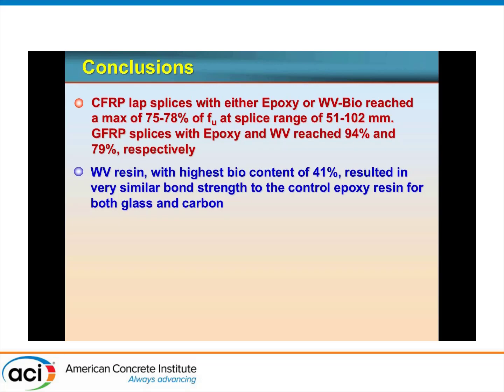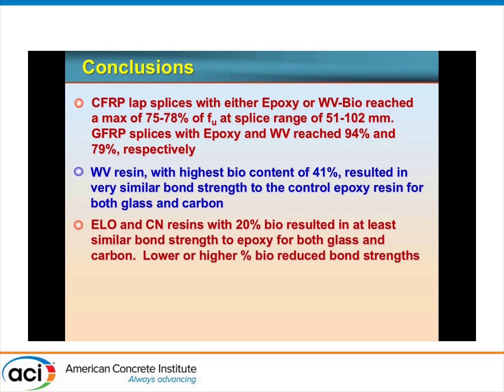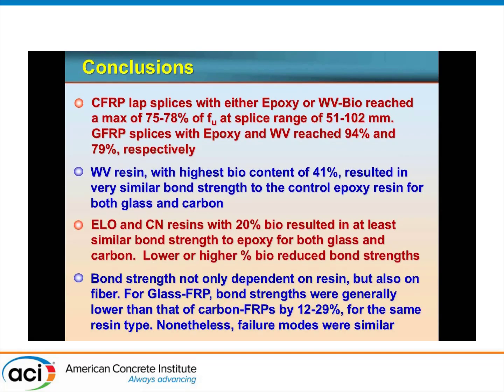The WV resin with the highest bio content of 41% resulted in very similar bond strengths to control epoxy for both glass and carbon. And that's bond to concrete. For ELO and CN resins with 20% bio, it resulted in at least similar bond strengths to epoxy for both glass and carbon. Lower or higher percentage bio affected the bond strengths in a negative way.